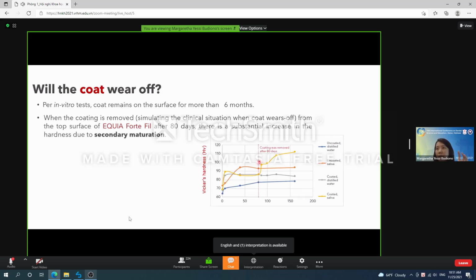And then at some point here, the coat was removed because it was worn off, right? You can see after the coat was removed, there is a huge jump in the hardness of the material. And this is why the benefit of this coat is actually very significant in increasing the durability and the wear resistance of the restoration.